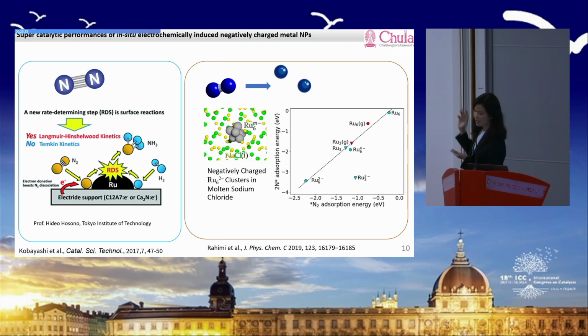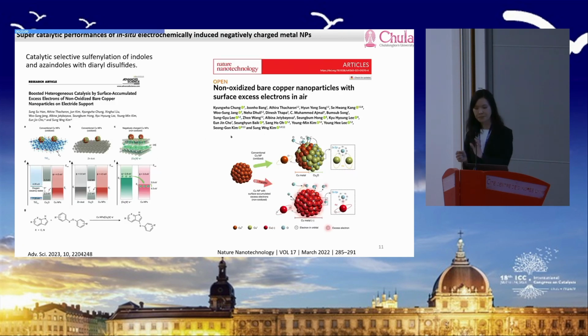Like on the right side, we have ruthenium clusters placed under molten sodium chloride. There are a lot of solvated electrons, so you end up with negatively charged ruthenium. And again, this ruthenium exhibits very superior nitrogen dissociation activity. More recent work has shown applications of this excess surface-accumulated electrons on metals in some organic synthesis. On the right side, it showed that these surface electrons keep copper from being oxidized even under ambient air.